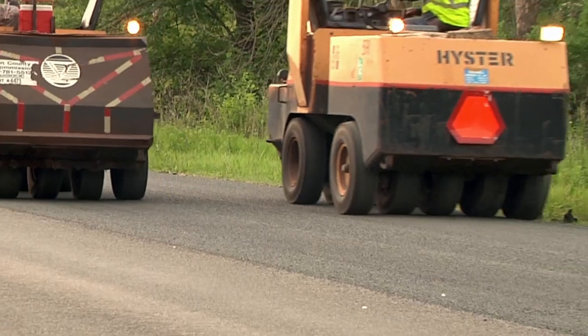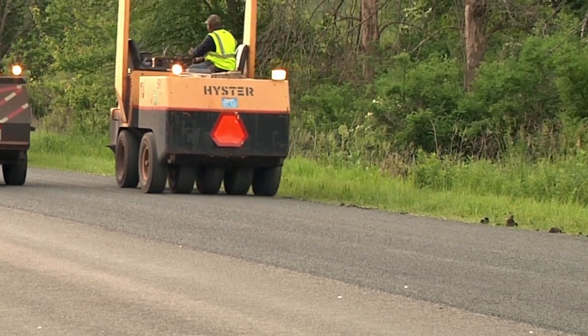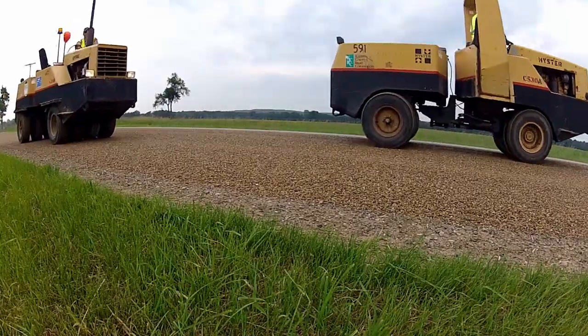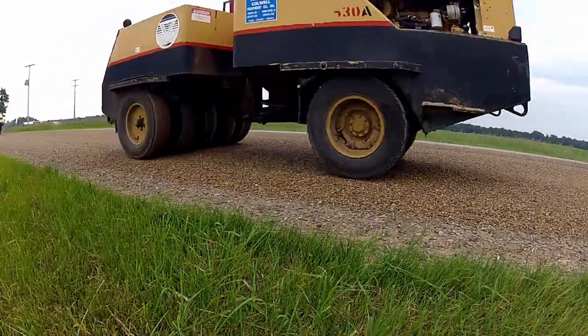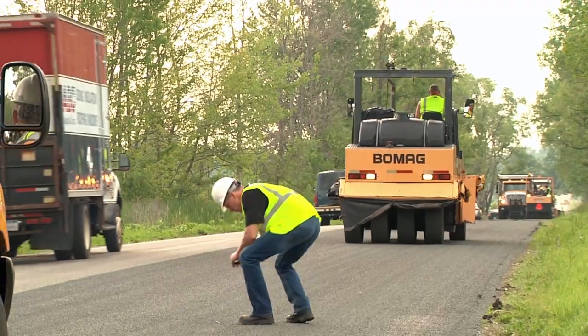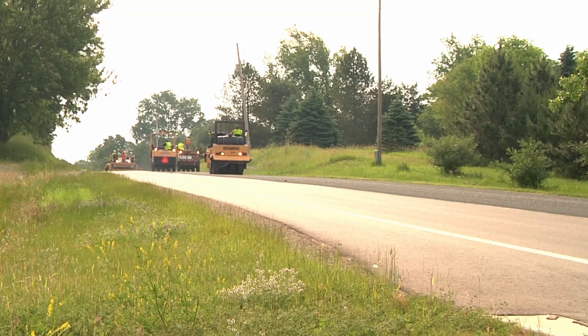Ensure rollers are staggered in echelon to provide uniform coverage over the width of the treated area. Make sure that the rollers embed the aggregate before the emulsion begins to break and inhibit proper embedment of the aggregate. The roller speed must never exceed 3 miles per hour.